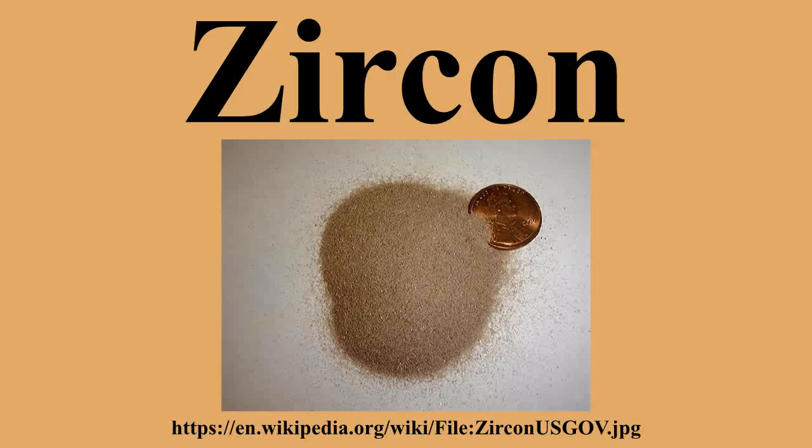Zircon is also very resistant to heat and corrosion. Because of the uranium and thorium content, some zircons undergo metamictization, connected to internal radiation damage. These processes partially disrupt the crystal structure and partly explain the highly variable properties of zircon. As zircon becomes more and more modified by internal radiation damage, the density decreases, the crystal structure is compromised, and the color changes. Zircon occurs in many colors, including reddish-brown, yellow, green, blue, gray and colorless.